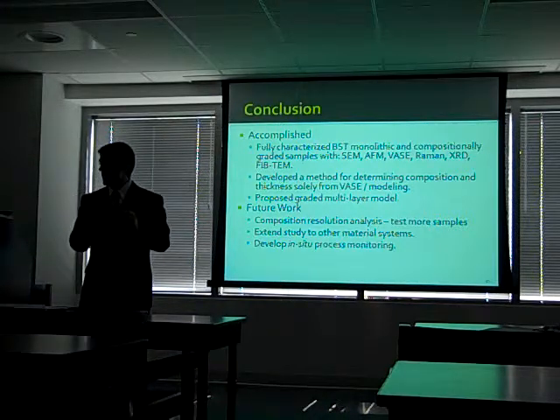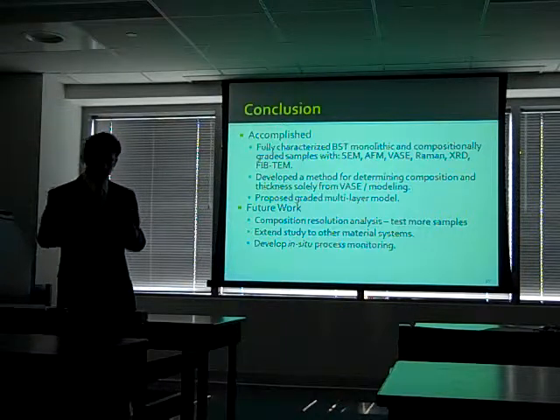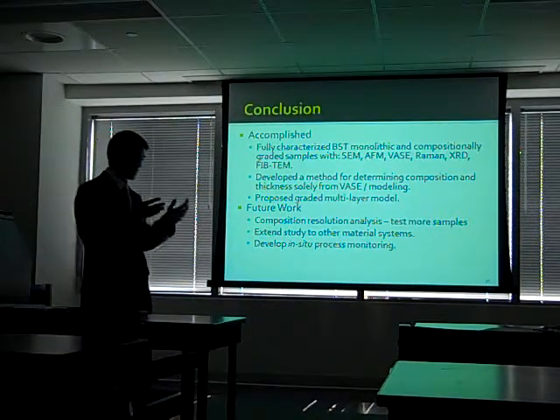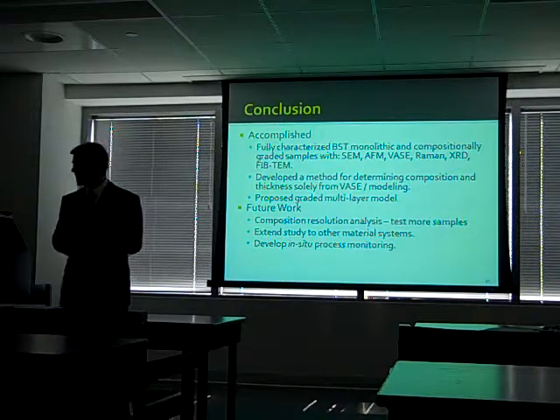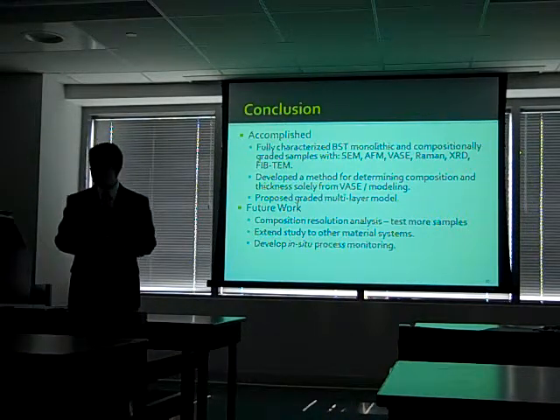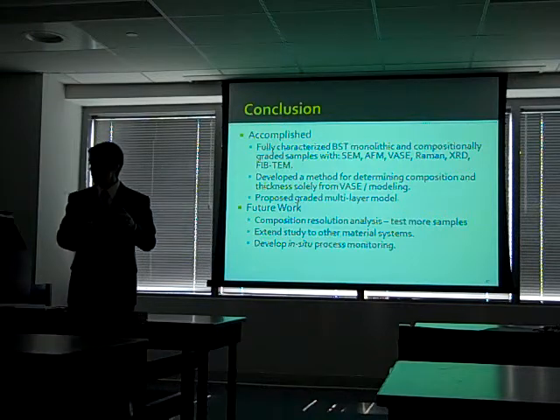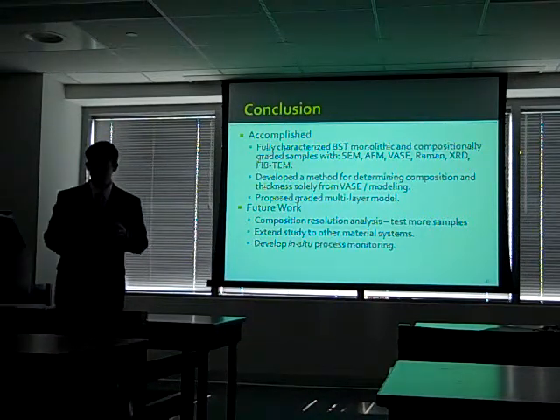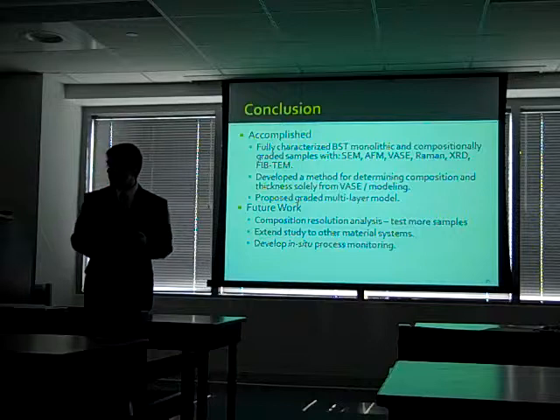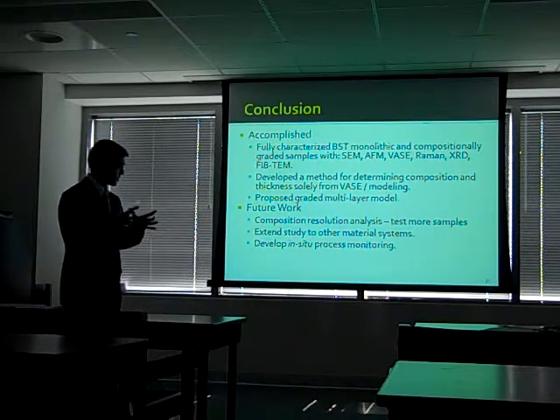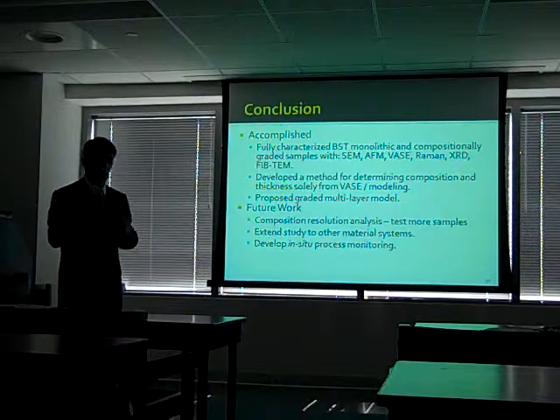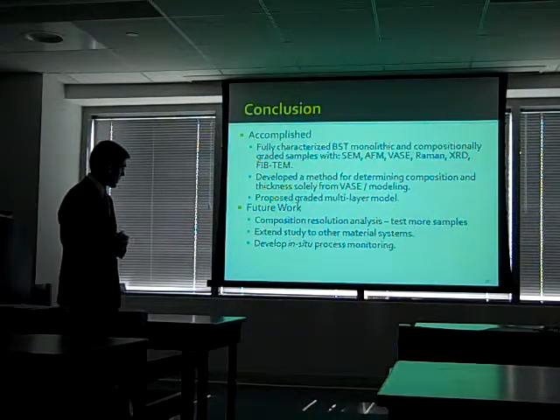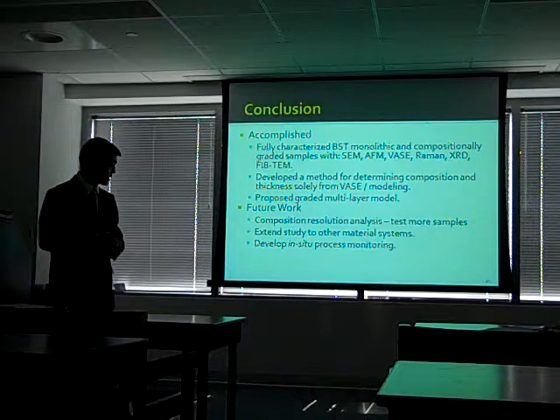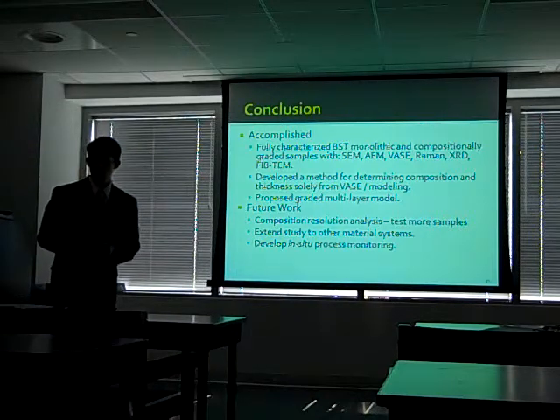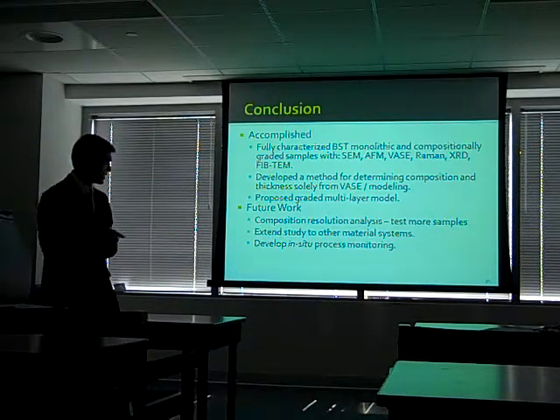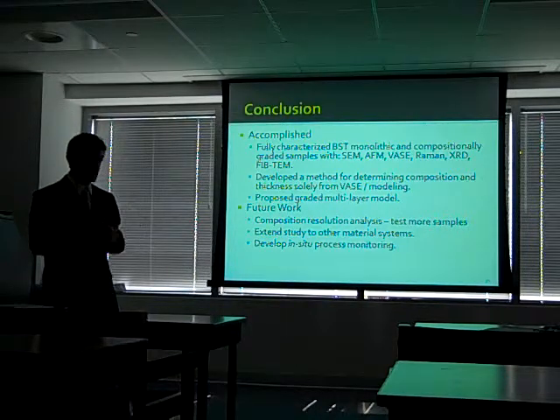So we're aware that error is introduced from the extrapolation of the bandgap using the top plot, and also from the non-zero mean squared error. As a result, we're not yet sure of the composition resolution that this technique is capable of, and also there hasn't been a sufficient sample set to test statistical variation. So for future work, it would be great to address this composition resolution analysis, maybe to have some more samples to, again, get some statistical variation, and then to address the known sources of error.